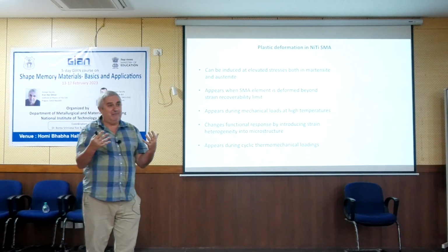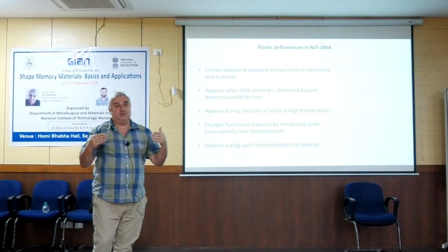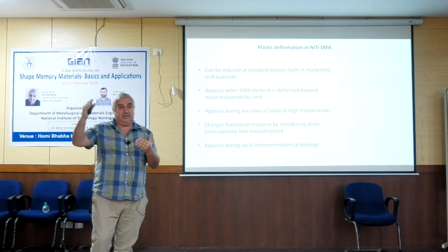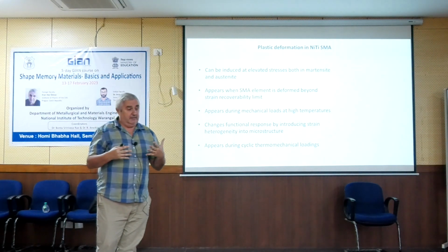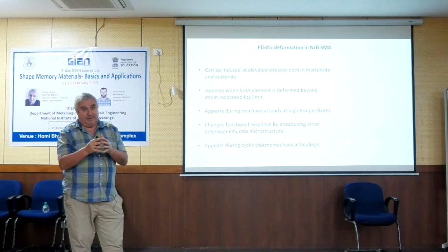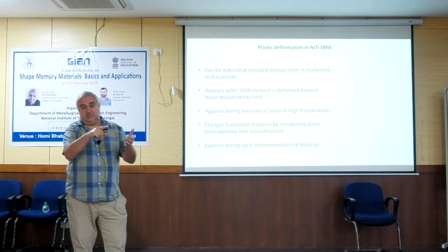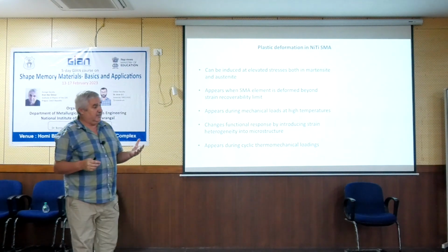So there is a problem: how to capture this kind of microstructure evolution, which is connected with plasticity, and this is irrecoverable. This is here until you heat it to 500 Celsius. It will stay here and it will accumulate. And it can tremendously, I mean, the microstructure which could be created by that plasticity could be very, very important, and it will change the behavior from this type to this type. So it will affect very significantly.